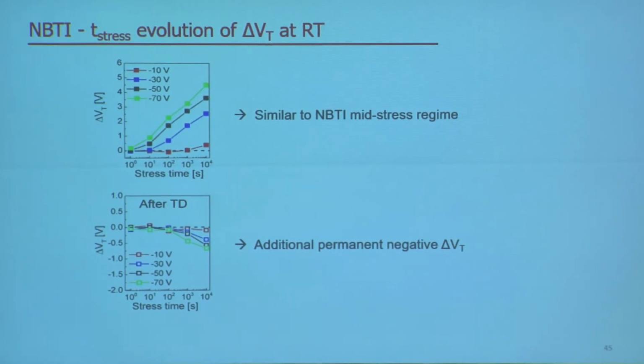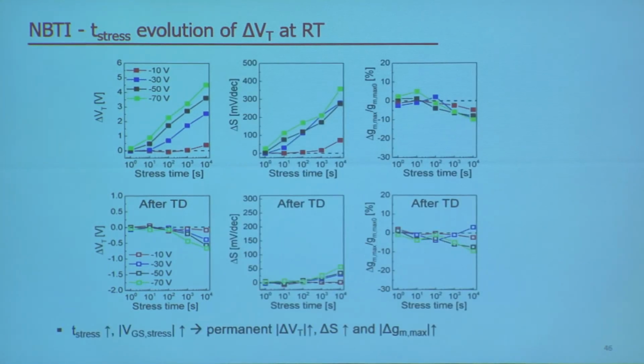So for NBTI, we first again look at the room temperature data, where we stress the device from -10 to -70 volts. So what you see here is really very similar to the mid-stress regime I talked about earlier, regime 4, where you see a positive VT shift. But for each one of them, we have also extracted the permanent portion, which we collect after thermal detrapping, and you see that there's a permanent portion of delta VT that also increases with stress time and stress voltage. We have done the same with the two other parameters, which are delta S and delta GM. Both parameters have permanent degradation, and they all increase with stress time and stress voltage.